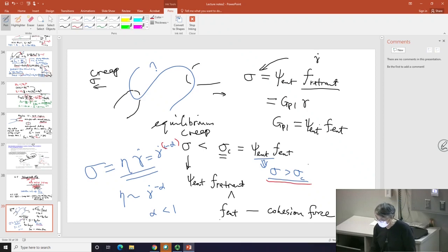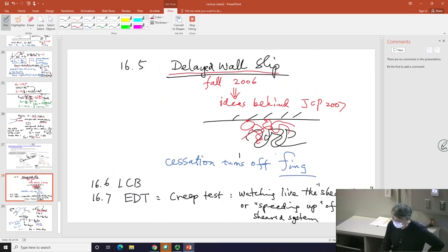The elastic state is not possible to survive, just by definition. Remember, this is the expression for elastic state, if you like, right? So that's why eventually you have to disentangle. That's why you have, by definition, a change from entangled state to disentangled state. The definition is an entanglement-disentanglement transition. There's no controversy for that.